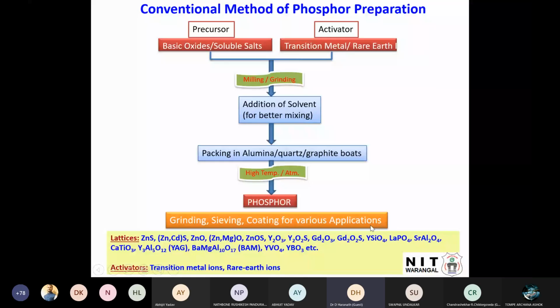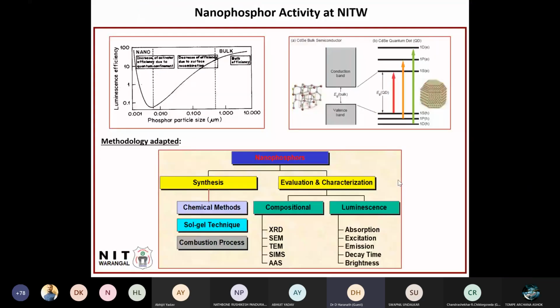So why should we go for nano when bulk materials are good? The only thing is, here you can see the efficiency, this is the luminescence efficiency. Efficiency of bulk is very good. Most of our displays use the same. When you decrease the size of these particles by grinding, this is the particle size, you will be losing efficiency. But if you can prepare the same in the nano regime, then you can see the efficiency is much better than the bulk. The intensity may increase a lot. So there are certain evidences, and you can have transparency for these materials. So many other things come into the picture. That's why people go for nano.